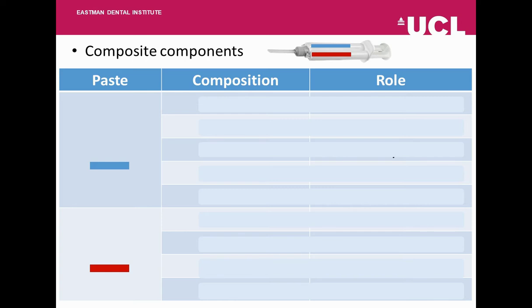So the composite components, and why our composite requires a double-barrel syringe. The double-barrel syringe is required because our composites are very similar to tooth filling composite, where light is required to cure the paste into a solid. Our composite cannot be used via light cure. One of the obvious reasons is because it's applied inside the body, and it will be difficult to apply UV light within the fractured site. So we have an initiator and activator phase. Once mixed, that's what starts the paste to set into a solid form.